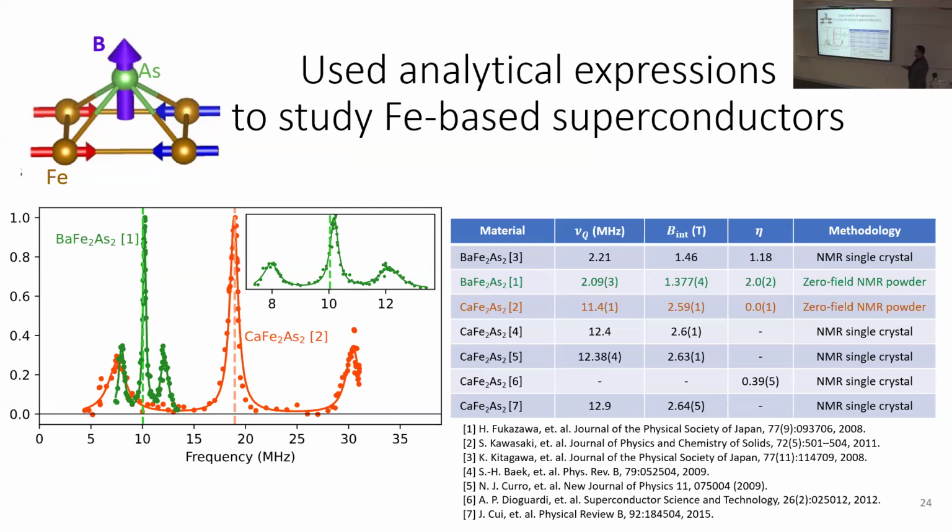These were done at cold temperatures using a powder sample. All they did was excite the system. Using these, we were able to extract not only the EFG easily, but also this nu Q, which is proportional to the VZZ component, this eta, which is the EFG symmetry parameter, and the internal field, using the equation that we derived.